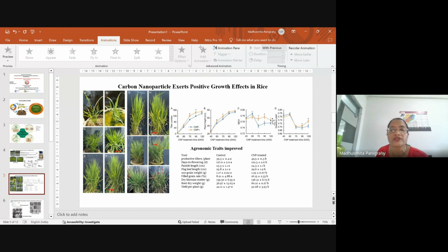In addition to the growth effects, we have also seen that different agronomic traits like productive tillers, days to flowering, panicle length, flag leaf length, filled grain weight, dry biomass, and root biomass, along with the yield, increased significantly in the CNP treated plants, which comes to nearly 17.5% yield increase in the rice plant. After this visible effect, we wanted to know the molecular mechanisms of how this carbon nanoparticle exerts this kind of positive growth effect in the rice plant.